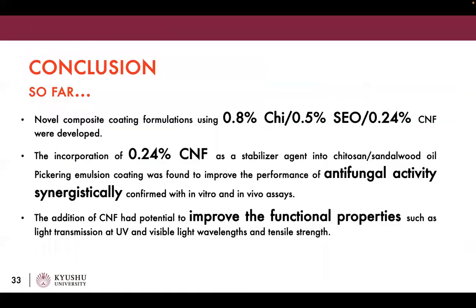And the conclusions of this chapter are: a novel composite coating formulation using 0.8% of chitosan, 0.5% essential oil, and 0.24% cellulose was developed, and the incorporation of cellulose as a stabilizer agent into the chitosan and essential oil Pickering emulsion coating was found to improve the performance of antifungal activity synergistically, confirmed with in vitro and in vivo assays. And the addition of cellulose nanofiber had potential to improve the functional properties such as light transmission at UV and visible light wavelengths and tensile strength.